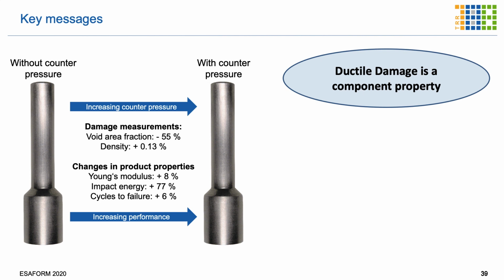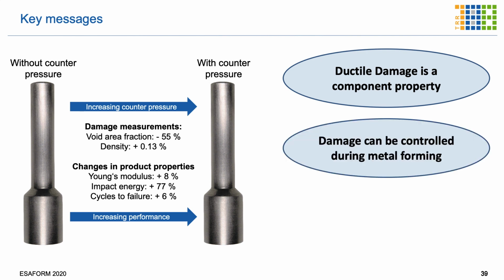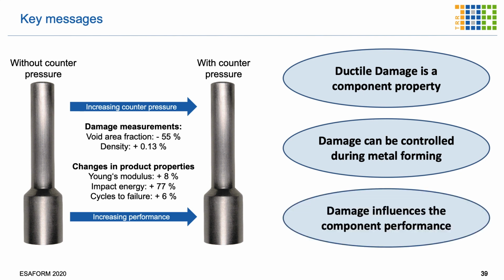And the key messages I can give you at the end is ductile damage is a component property. Damage during metal forming can be controlled by process parameters and process design. Damage influences the component performance significantly, as shown in this example with counterpressure and no counterpressure here.